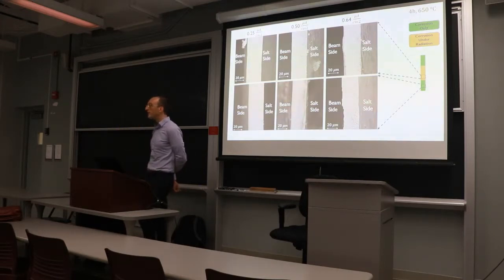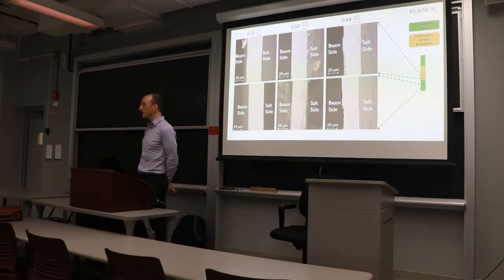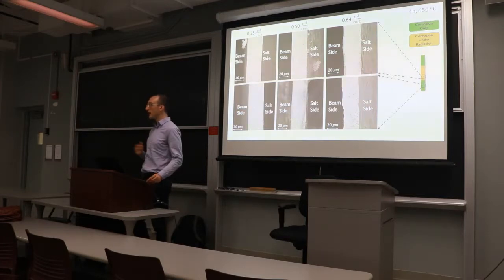Yes, you? Has there been any control runs of just basically putting the ion beam on a plate for 4 hours at 650? And on a similar line, I don't know how you do it with the setup, but having an isolated circle just in the very middle, and having a control run with no beam, and then an isolated circle control run with the beam. So the answer to your first question is yes. We do about 1 control run for every real experiment. And so we do lots of no-beam corrosion experiments. For example, we tried changing the europium tri- and difluoride potential to just get the effect of europium potential on corrosion. And we just use this beam line as a little molten salt chamber for that.